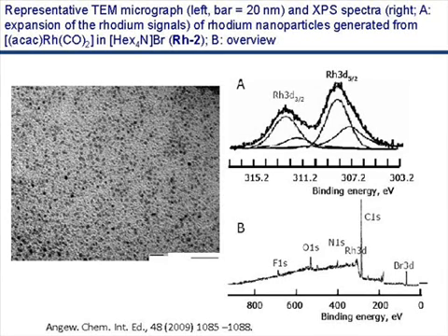And after that, sorry, I will come back to another point which is extremely important here. We were able to hydrogenate because Walter is very well known for CO2 supercritical conditions, and he said, why not try to repeat this hydrogenation, not only with hydrogen, but in CO2 and hydrogen. And we went to Walter and we repeated this reaction. And what we got, we preserved the cis double bond unaffected, but instead we hydrogenated the aromatic ring. From a thermodynamic point of view, it's unusual, because when you hydrogenate styrene, for example, you will hydrogenate the double bond and you will keep this.